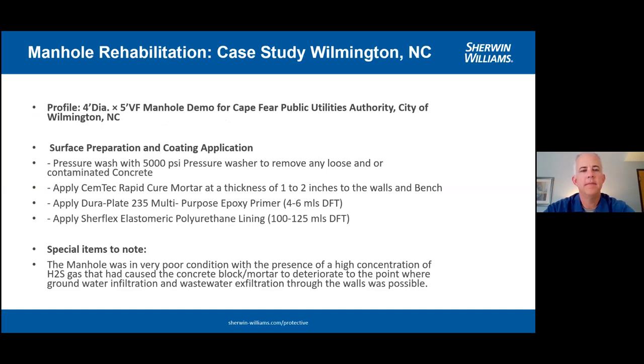So let's look at a case study. In the short version of it, and I'm not going to read all of this, this was about a 5 vertical foot deep manhole, 4 foot diameter. The summary of what we did with this one: for surface prep, we did not do abrasive blasting when we went down in this manhole to rehabilitate it. We pressure washed it with 5,000 PSI water to remove any loose or contaminated concrete. We did a mortar rehabilitation. We applied a primer. And then again, because this one was in a roadway, we used a polyurethane liner to go down in this hole.